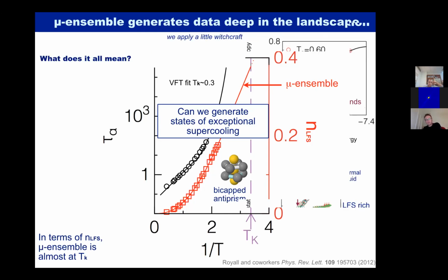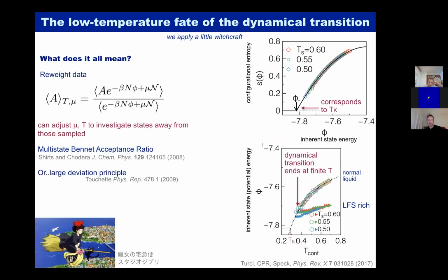This is a rather hand-waving argument, but we've actually done this in much more depth. I don't have time to go into it now, but what we have done is to create an ensemble by which we can generate data at extremely low temperatures and very long relaxation times, much longer than one can obtain with conventional computer simulation, maybe 10 orders of magnitude longer. What this enables us to do is to look at what happens in the system at these states of very deep supercooling. Shown in the top right is the configurational entropy as we drop the inherent state energy, which is the energy of the system.